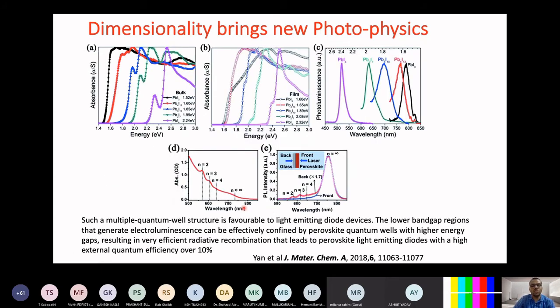So this is the data which is shown, dimensionality brings new photophysics. When people started mixing this kind of larger molecular cation, they could see the absorption spectrum on the energy axis. As you go towards the shorter wavelength side, you have a dominating excitonic feature as well, and you are seeing those step kind of functions. Step functions are seen in an absorption band gap when the material has 2D character. When you have 3D materials, your density of states goes as E to the power half. When you have 2D semiconductors, it goes as a kind of staircase.